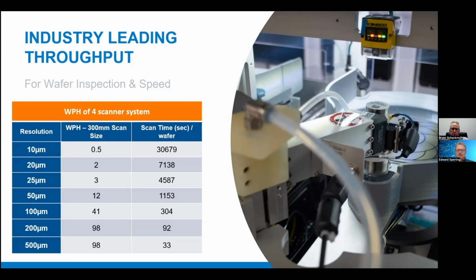So there's no turnaround time. It's a continuous scan that's not stitched together. And that's what allows us to get the really high throughput. The main thing that most customers are looking at, like at 100 microns, we're getting 41 wafers per hour. The previous systems were getting somewhere in the 5 to 8 wafers per hour. So there's a big multiplier in the throughput we can achieve with this method.